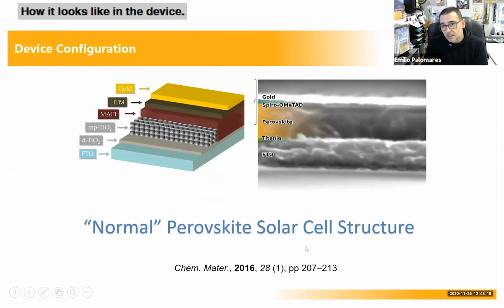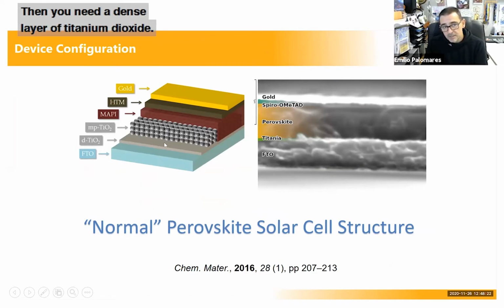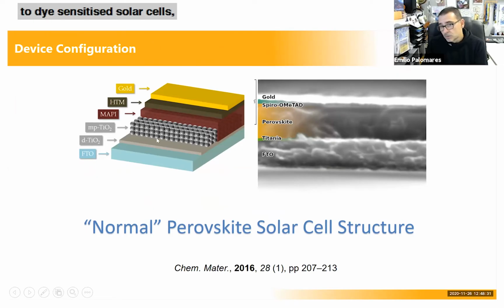How does it look in the device? Well, this is the FTO, the fluorine-doped tin oxide. Then you need a dense layer of titanium dioxide. You still need a thinner mesoporous titanium dioxide layer. This resembles dye-sensitized solar cells. Then you have the methyl ammonium lead iodide. This is what is called the perovskite. You need the hole transport material, for which people usually use the spiro-OMeTAD. This is the molecule that people use as a standard. And then you use a metal contact.